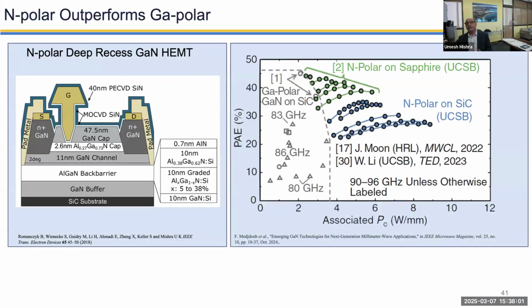So nitrogen polar GaN actually turns out to be quite spectacular. Here's an example of gallium polar GaN. It hits a wall in watts per millimeter and efficiency. This is where it is. But nitrogen polar GaN on silicon carbide and on sapphire is spectacular. You can see that at 5 watts per millimeter, you can get more than 40% power added efficiency. And in fact, at 3.7 watts per millimeter, this slide is a little old, I'm sorry, I didn't update it, but now we have 52% power added efficiency. So you can see how nitrogen polar GaN just broke through the wall that was holding GaN.